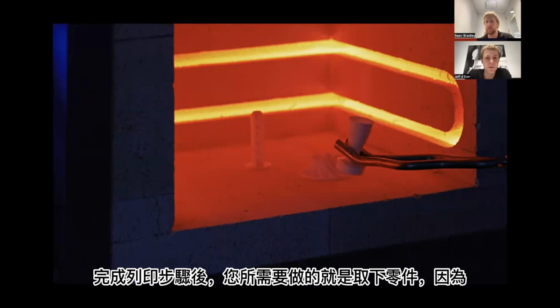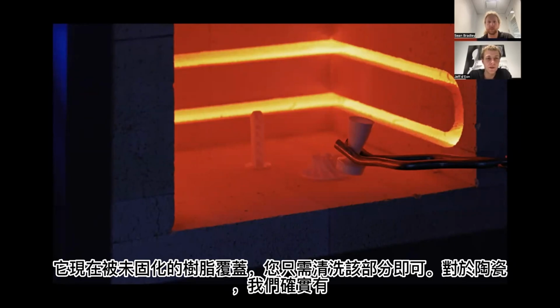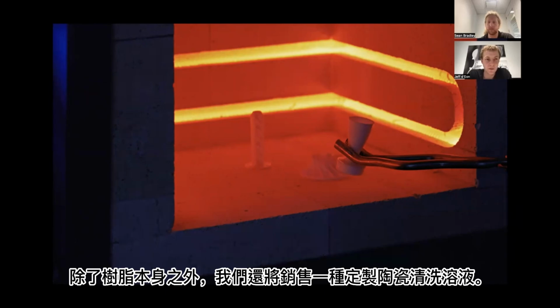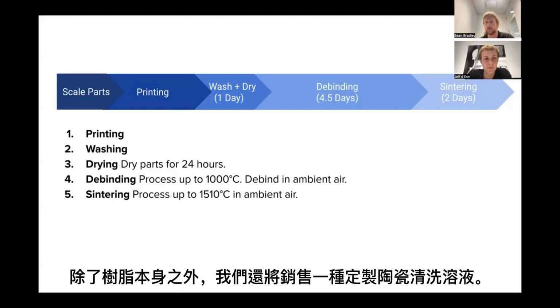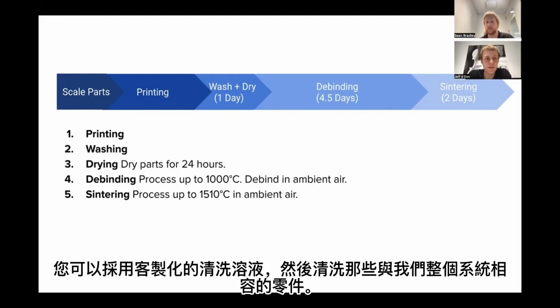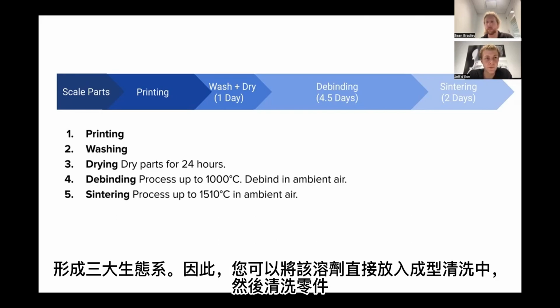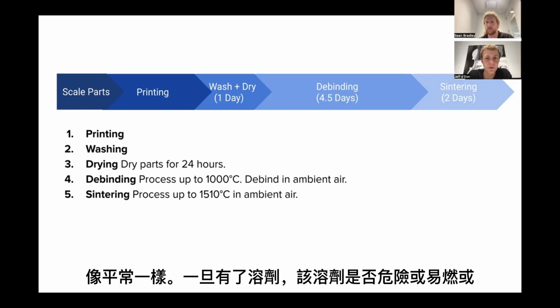Once you're done with the printing step, all you need to do is take the part off, and since it's now covered in the uncured resin, you just need to wash that part. For the ceramic, we do have a custom ceramic wash solution that we will be selling in addition to the resin itself. You can take that custom wash solution and then wash those parts. It's compatible with our entire Form 3 ecosystem, so you can put that solvent directly into a Form Wash and just wash your parts as you normally would.